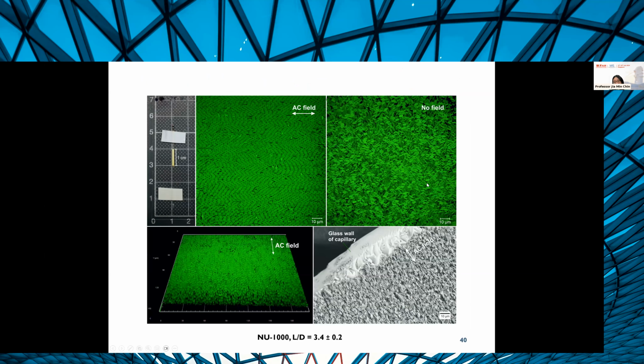And in the absence of an E field, you see that they go pretty much every which way. However, these particles are very monodisperse and they have a higher monodispersity than is required to form the smectic phases I showed you earlier. So here you do see a little bit of a tendency towards the formation of layers if you look at these adjacent layers here. But if you look at it closely, the neighboring particles are not perfectly standing next to each other like soldiers, but rather they're shifted or staggered relative to each other.